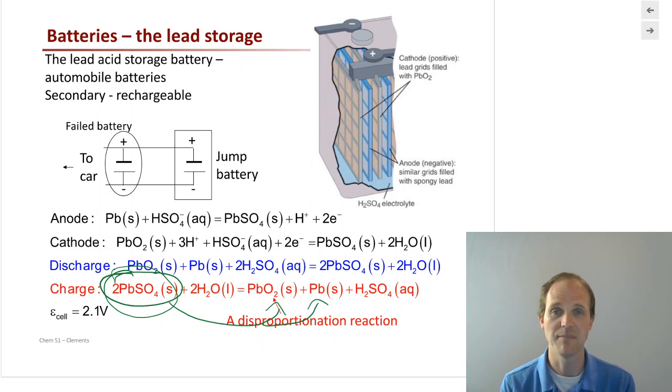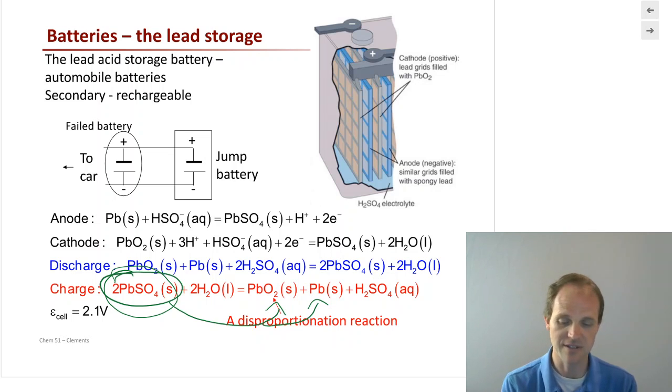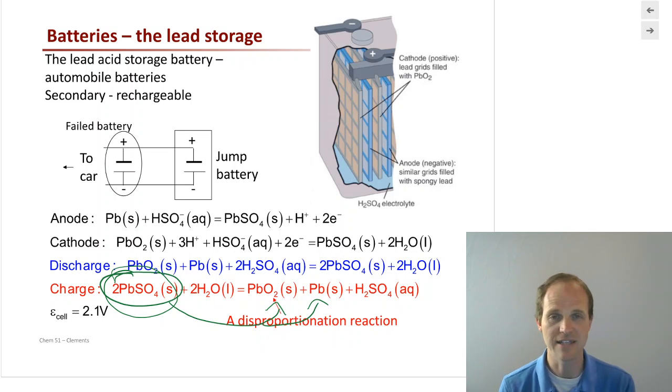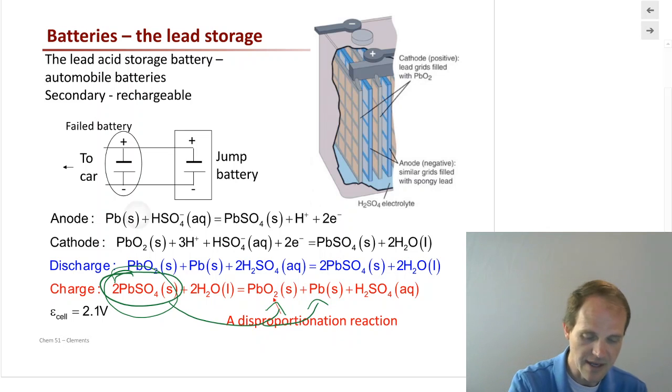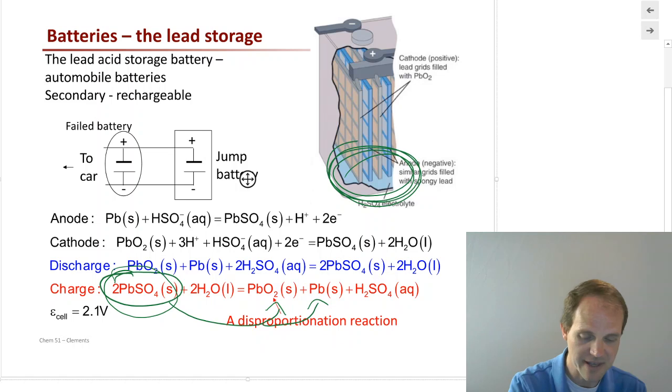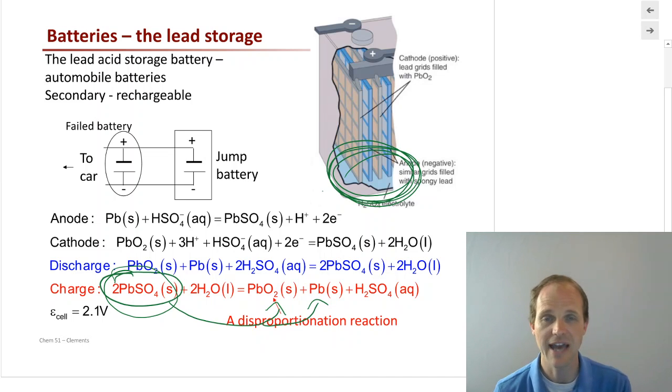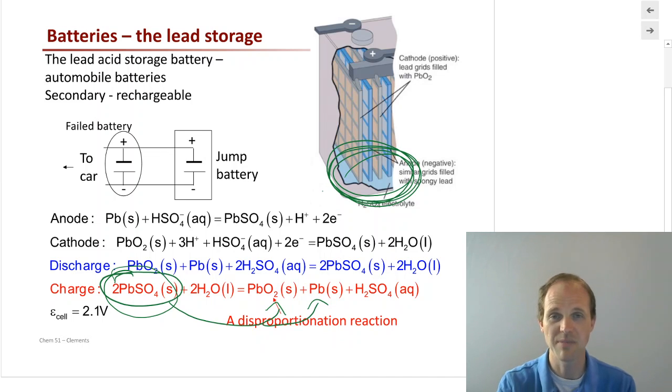They're all lead batteries working on lead going to lead 2 sulfate, lead 4 oxide going to lead 2 sulfate, and then backwards again. The primary difference between those different batteries is how much space is on the bottom to catch the lead sulfate before it piles up enough that it short circuits your battery. Okay. Yes, there's a little bit about how much material there is and things like that, the thickness of it. But one of the primary things is how much space are you paying lots of money for?